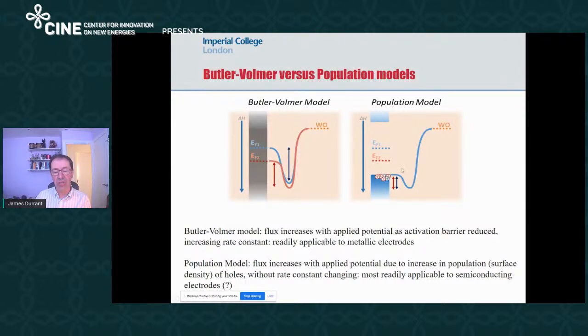There's an alternative model which has been particularly developed by Nate Lewis, but it really comes from the thinking of Gerischer at some time before, which is the idea that if you have a semiconductor and you apply a more positive potential, the main thing which happens is that the Fermi level approaches the band edge, and so the density of charge goes up. And so in this model, there's no change in activation barrier in the simplest case, and so the rate constant stays the same, and what's changing is the population. And most analyses so far of kinetics of water oxidation have been applying the Butler-Volmer model.